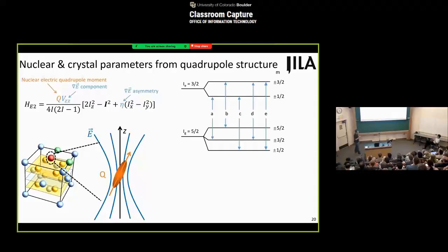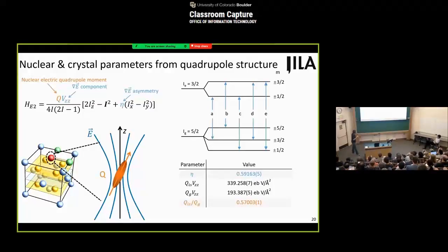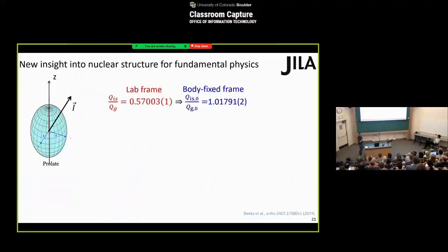By fitting our experimental data to this Hamiltonian, we can extract these parameters, where eta is purely an asymmetry parameter that depends on the crystal structure, and we can get the QVZZ product. But they depend both on the nuclear properties and the crystal properties. So if we take the ratio, we can get a number that is only dependent on the nuclear properties. So this ground to excited state quadrupole moment ratio actually tells us something about the nuclear structure.